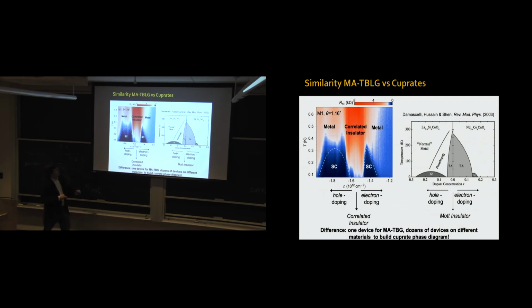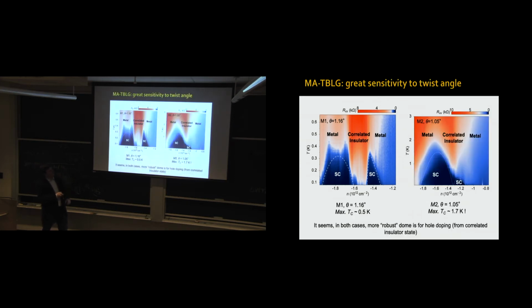Now this situation I'm depicting here, where these two domes are similar in size—usually we actually have a situation much more asymmetric, where we have a much smaller superconducting dome for electrons than for holes. In these cases, we also have substantially higher critical temperature for these angles. Our highest critical temperature when we reported this data was 1.7 Kelvin. I'll show you more data in a moment.